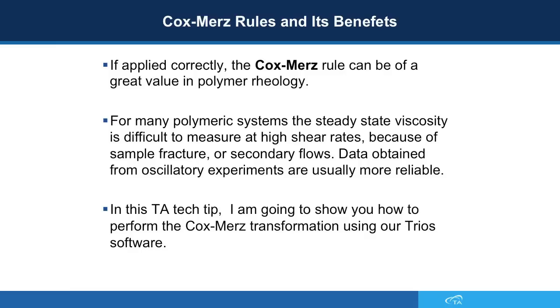If applied correctly, the Cox-Merz rule can be of great value in polymer rheology. For many polymeric systems, the steady shear viscosity is difficult to measure at high shear rates because of sample fracture or secondary flows. Data obtained from oscillatory experiments are usually more reliable.